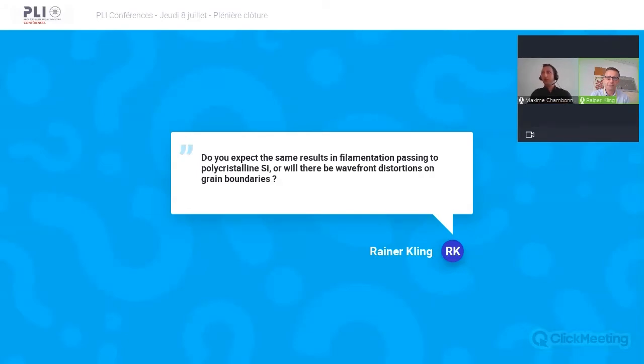Well, that's a good question. Actually, nobody in the past studied the influence of the polycrystalline features of silicon on the filamentation. I would expect, as you mentioned, that there could be some wavefront distortions on the grain boundaries, depending on the size of the grains compared to the wavelength, of course. So for solar cells, the dicing is even more challenging than what you showed on the monocrystalline, right? I would say so, but without any experimental evidence. But this is something that should be tried in the near future.